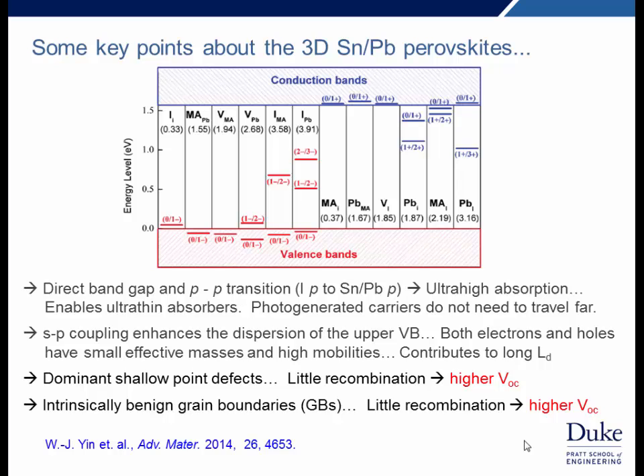Additionally, if we look at defects, the dominant defects are very shallow, and so this contributes to not much recombination and therefore higher VOC. And likewise, the grain boundaries are predicted to be benign in this material for similar reason, namely grain boundaries locally can look like interstitials or vacancies. And so this, again, gives rise to the high open circuit voltage.